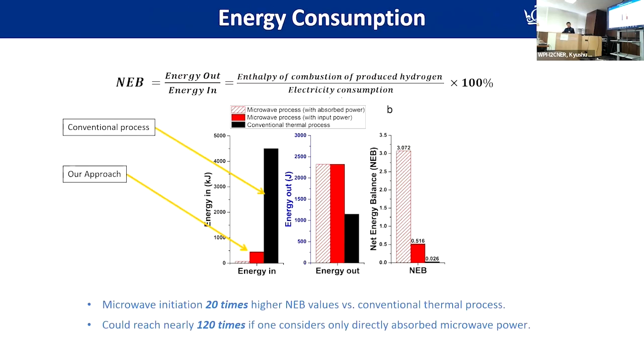Energy-wise, we can very simply compare with the electric furnace in the lab, and we find the microwave could achieve 20 times higher energy efficiency compared to conventional thermal heating if we compare the full input power. But if we only consider the power actually absorbed by the samples, it could be as high as 120 times. Because under laboratory conditions, we can only do very high power generation with smaller samples, we haven't done the impedance tuning. That could be easily achieved by the engineering design of the microwave. So that also indicates how energy efficient it could be.